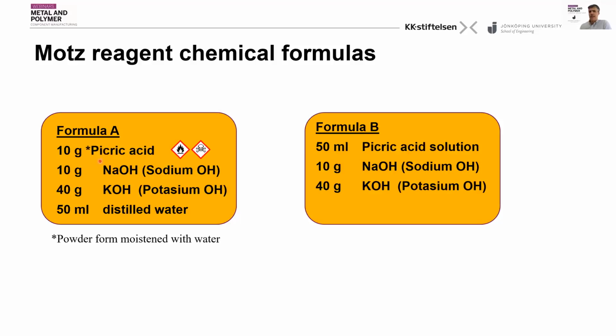And the picric acid is in the form of powder that is moistened with water. This is flammable and also toxic. For this reason, there is also a second formula, formula B, in which we are using instead 50 milliliters of picric acid solution, 10 grams of sodium hydroxide like before, and 40 grams of potassium hydroxide. The difference between these two formulas is that formula A can be used several times, while formula B loses its potential after a couple of uses.